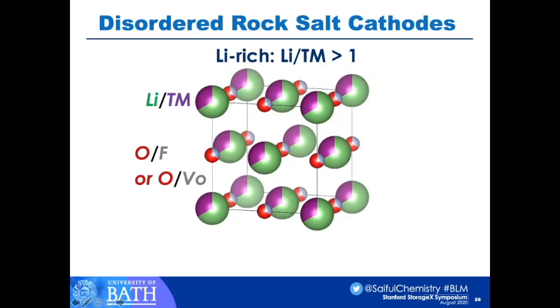So the other area, as well as the lithium-rich layered, are the disordered rock salt cathodes. And these were introduced with an elegant talk, as always, by Gerbrand Ceder. Essentially, you've got the classic rock salt structure, and in that rock salt structure the cation sites are occupied by a mixture of lithium and transition metal ions. The anion sites are occupied by oxygen and fluorine for the oxyfluorides, and for the pure oxides, there might be oxygen vacancies as well.